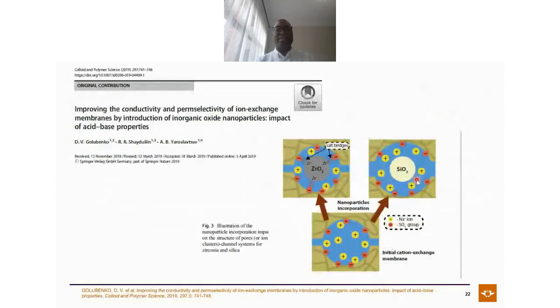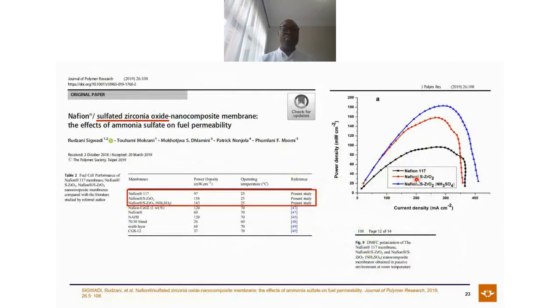Well, we looked at this and said, these are the membranes that you've been doing. So let's have a look at what will happen if we add this different type of nanomaterial to Nafion. Can we improve Nafion? Well, we took Nafion and added sulfonated zirconium oxide to the Nafion. As you can see, we were able to get almost 200 power density when we're using zirconium oxide, which is a metal oxide, based on the properties that we've already spoken about. So this nanomaterial was able to improve Nafion.